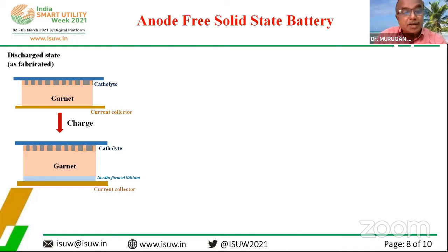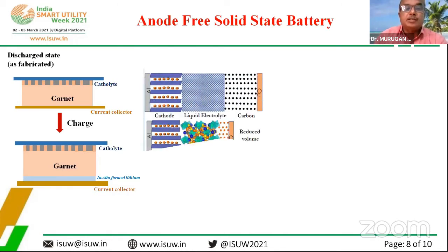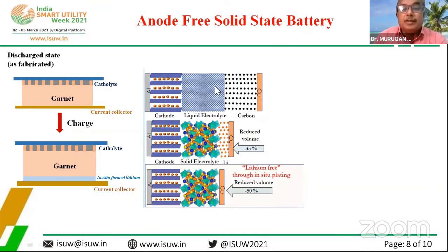So the advantage of having this anode-free engineering is, if you look into the conventional liquid electrolyte, if 100% is the size, you can bring down the volume by 35% by just putting a small layer of metallic lithium instead of the large volume of graphite. But by means of this anode-free engineering, we can reduce the volume by 50%. And what we are working on now is a total thickness of not even 120 micron or 110 micron. So that's the beauty behind this.